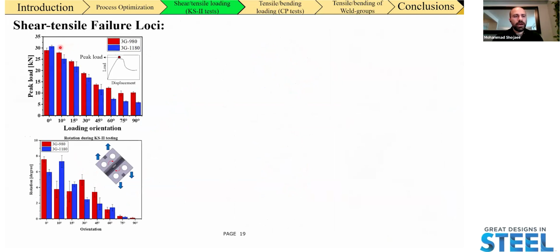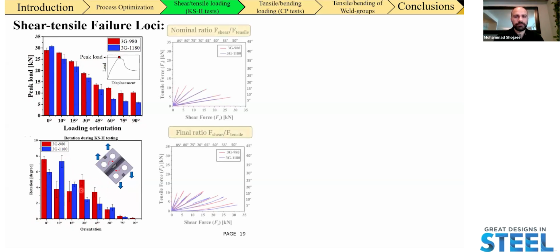So the output of this test is going to be the peak loads, as I've summarized here for both of the materials. The 3G980 is the one in red, and the 3G1180 is in blue, for all different loading orientations that we performed. And we also have the amount of rotation that we have until the onset of failure, as I've summarized in the graph at the bottom here.